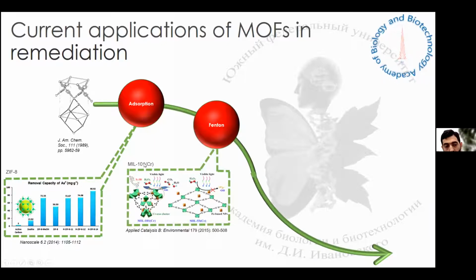The next example is Fenton, where we mostly have MIL materials used as a catalyst during the reaction. The Fenton reaction is where we need to activate hydrogen peroxide. This is MIL-101 based on chromium, and you can see it is easily activated by visible light and can decompose hydrogen peroxide to hydroxyl radical, then start targeting organic pollutants inside the solution or any other media that we have.